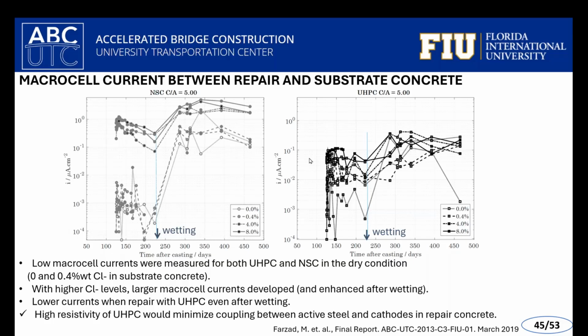So we have our substrate environment having different amounts of chlorides. For our normal strength concrete, when we initially have low level chlorides, the rates are very small because no chlorides are there. With high chlorides, the rates are significant. Upon wetting the sample, everything jumps up, and the corrosion rate can be significant with the normal strength concrete repair. On the other hand, when we have the UHPC repair in these scenarios, the corrosion rates are low, and even after wetting, remain low. Interestingly, this holds even when the substrate has a fairly adverse and high level of chlorides in the system.